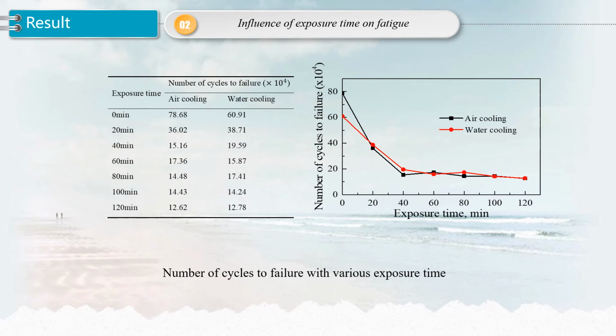This page shows the influence of heating duration on fatigue property of steel wire. As expected, the decreasing trend of fatigue with various exposure time is similar to that of strength. A decrease in the number of cycles to failure with increasing exposure time was observed.